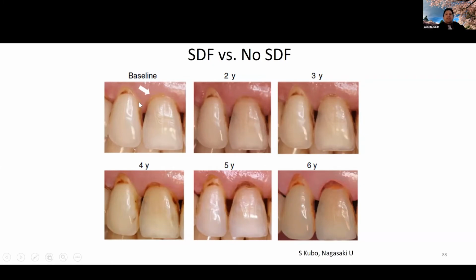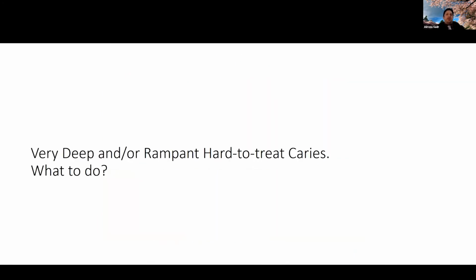So they went ahead and followed up this case for 6 years. And it's interesting, after 6 years where there was an increased issue with the xerostomia, so dry mouth in this particular case, you see that there is obvious caries formation around the central incisor. Well, the area that was treated with silver diamine fluoride, and I think this was an annual application of SDF, was completely intact. So I hope this is a good way to kind of look at the potential effects of silver diamine fluoride on root caries prevention, especially for the elderly.